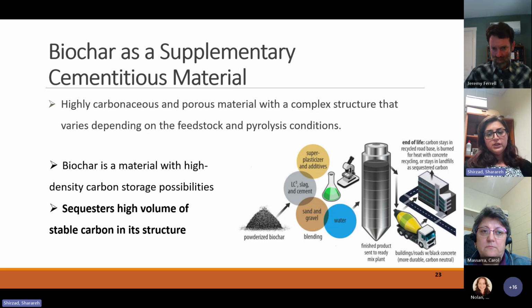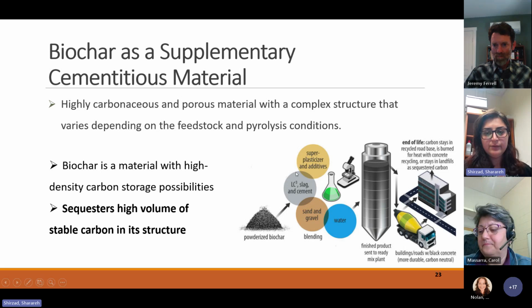So what we do for biochar concrete, we mix aggregate, sand and gravel with water, with biochar. And because biochar usually has a negative impact on workability and slump of the mixture, you end up using superplasticizers to help with improving workability of the mixture. Then we replace some of the cement with biochar, and then we mix everything. Then you place that mixture and make your concrete.